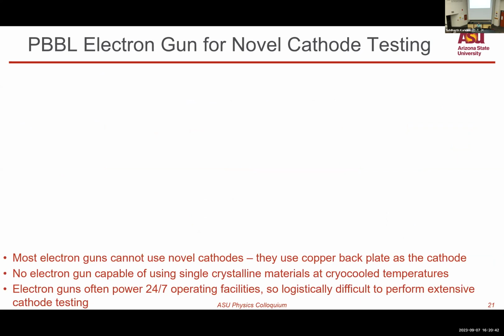Okay, finally, we have developed all of these novel cathode technologies. How do we get electron beams out of those? Most electron guns today cannot use these novel cathodes. They use the back plate of the gun, which is typically polycrystalline copper, as the cathode. They just shine light on the back plate. It's convenient. No electron gun exists other than the one that we have that's capable of using single crystalline materials at cryo-cooled temperatures, which is absolutely essential to get these low mean transverse energies that we have demonstrated.